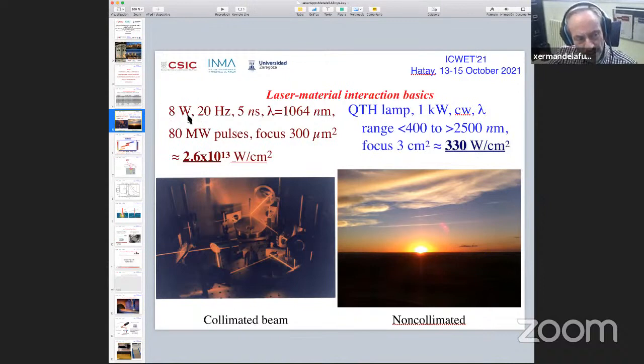But if you take an 8-watt laser, not 1 kilowatt, but just 8 watts, and you have it irradiate at 20 hertz, that is 20 pulses per second, in pulse mode, 5 nanoseconds pulse duration, with a specific emission wavelength, like in this case, 1064 nanometers in the near IR, then you can get 80 megawatt pulses. You can focus it to 300 square microns very easily. And if you calculate the irradiance value for this, it is 2.6 times 10 to the 13 watts per square centimeter. You can see it's about 10 orders of magnitude higher in irradiance than this 1 kilowatt lamp. This is what makes the difference between a laser and any other energy source.